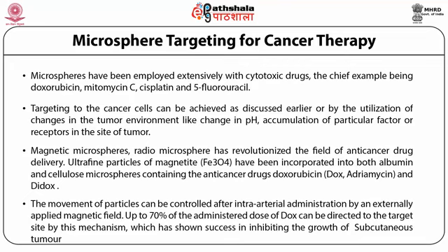Ultra-fine particles of magnetite, that is Fe3O4, have been incorporated into both albumin and cellulose microspheres containing the anti-cancer drugs doxorubicin and didox. The movement of particles can be controlled after intra-arterial administration by an externally applied magnetic field.